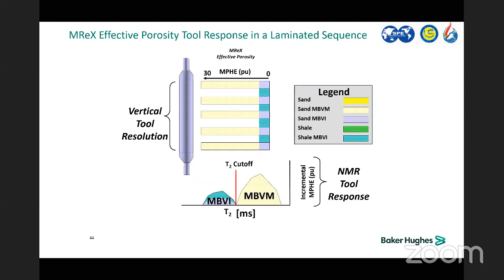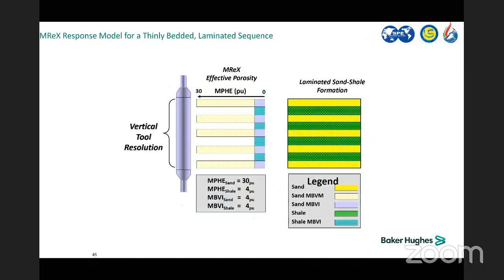So a simple technique, this is the conventional one. We apply the cutoff for T2. Above the cutoff is the free fluid. Below the cutoff is bound fluid. And you can see that after excluding the shale, the total porosity is 30 pu for the sand, and we have 4 pu for the effective porosity in shale. And the bound fluid for shale and sand is 4 pu.